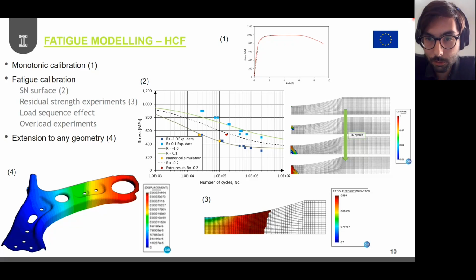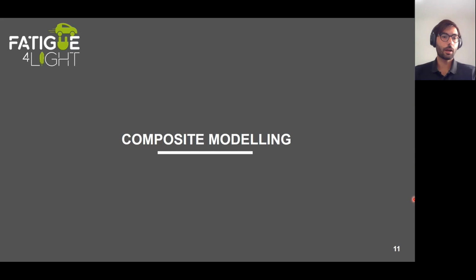And well, we have performed several different kinds of tests related to fatigue, as Sergio mentioned before, like the residual strength experiments, in which we apply a certain amount of cycles and then we load it monotonically to see what is the effect of this degradation. And actually, this result is in the lower right part of the slide, number 3. That zone, the colorful zone, would be the zone affected by cyclic loading as a decrease of this reduction factor parameter.